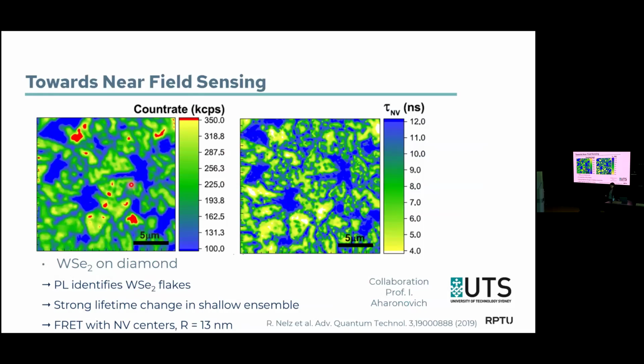But when we look here, everything that's in yellow or green is the stronger fluorescence of this 2D material. And what's blue here is the weaker fluorescence of our NV centers. If you then look into the lifetime of the NV centers, in principle, you see exactly the same picture again. And you see, indeed, under these flakes, the lifetime is going down. They're obviously not perfectly flat on the substrate because there's a lot of structure still, but this is from the transfer process. And we could even estimate the so-called Förster radius, which in principle gives you the distance where you have 50% of energy transfer. So this was the first time we saw this.